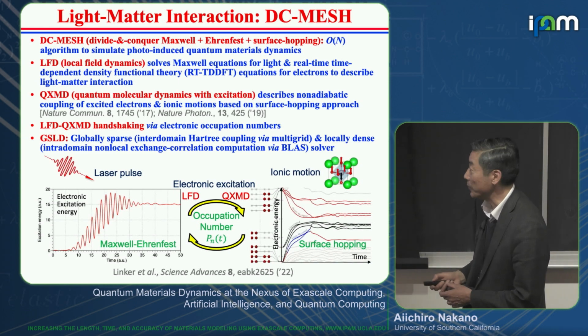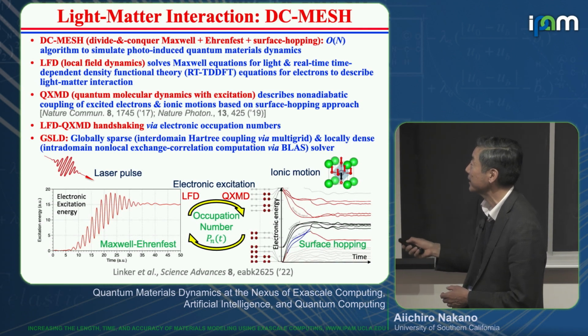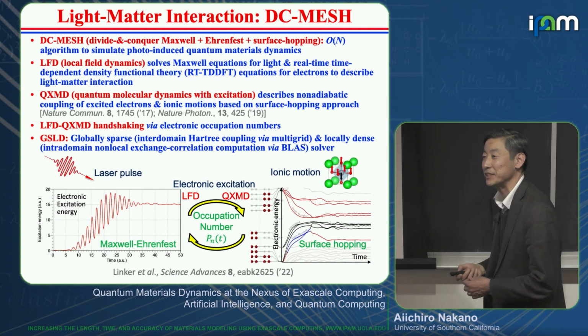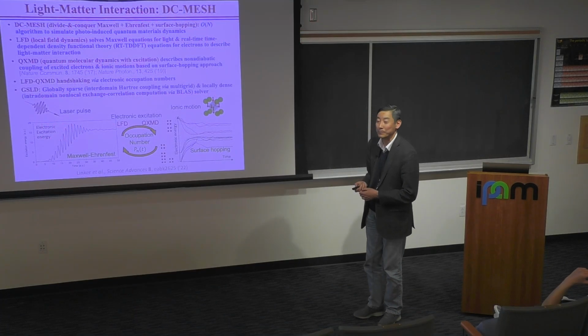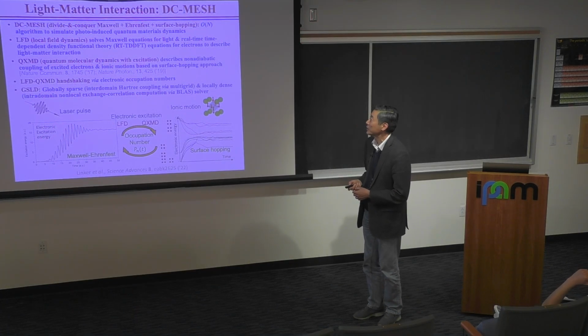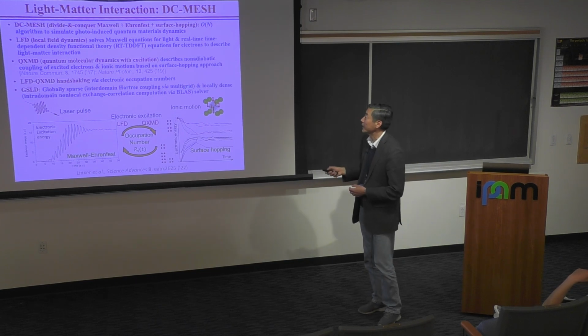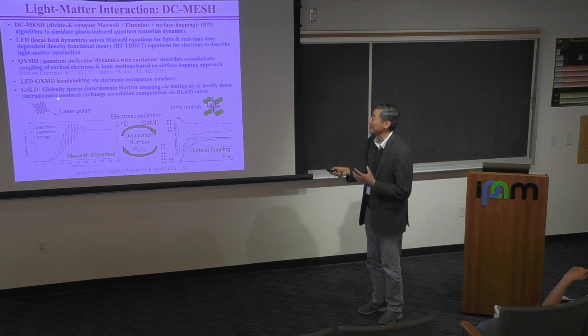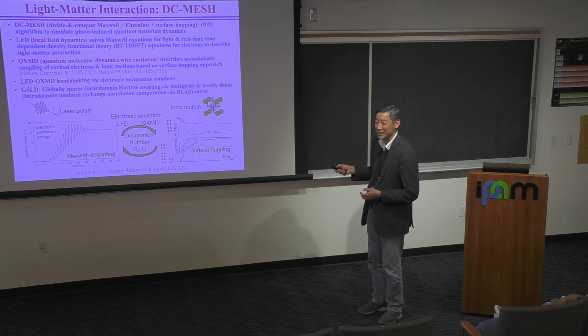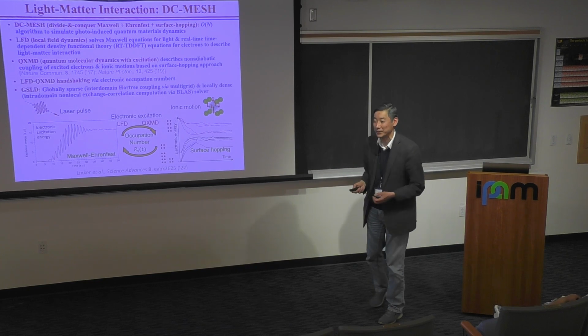And then here we also develop a so-called globally sparse and locally dense solver, which is again the key to scalability on modern exaflop architectures. Where inter-domain Hartree coupling is achieved, again, by a scalable sparse multigrid method, whereas the intra-domain, actually the heaviest computation, turned out to be the non-local exchange-correlation computation, and that was mapped to basic linear algebra matrix computation, so as to use a GPU.